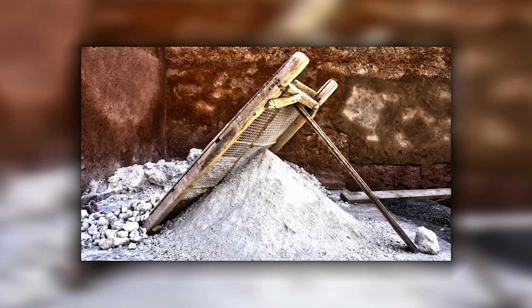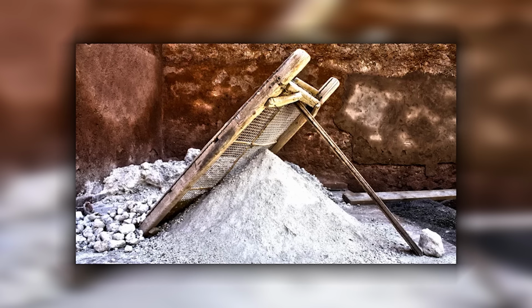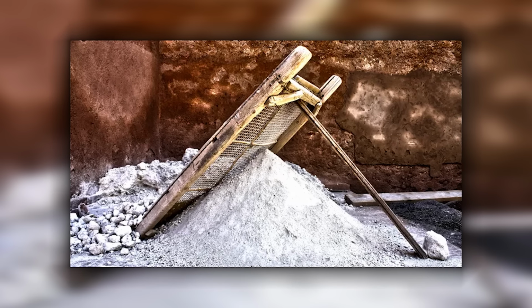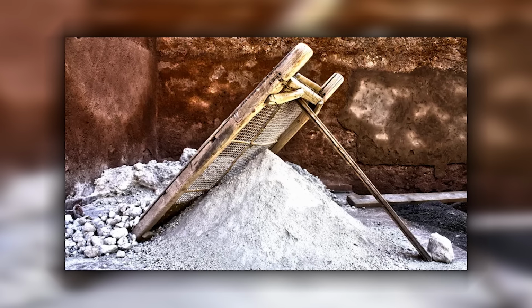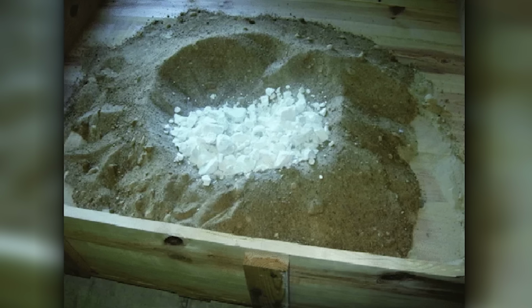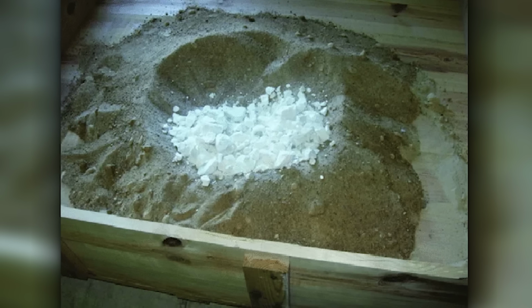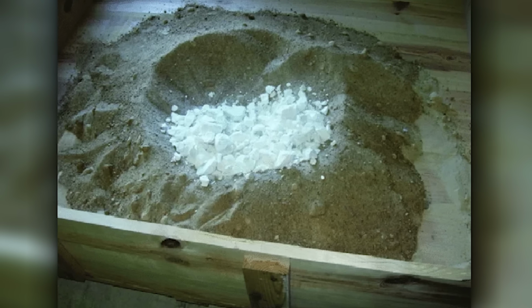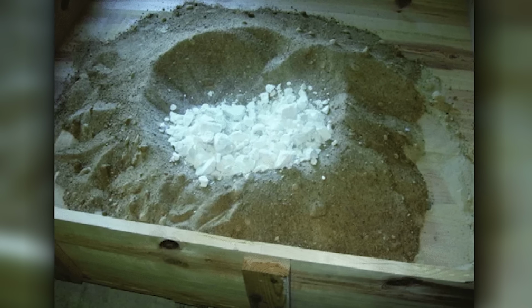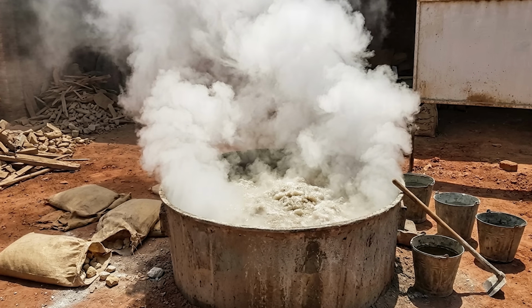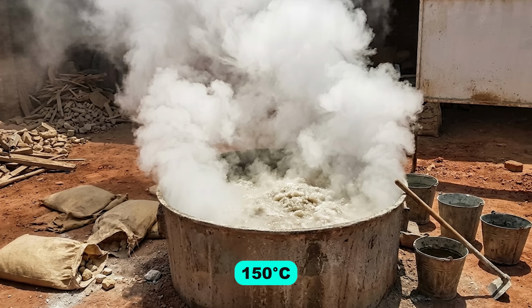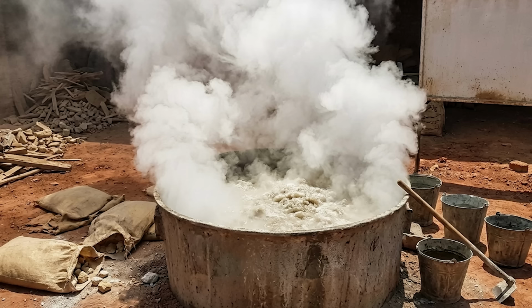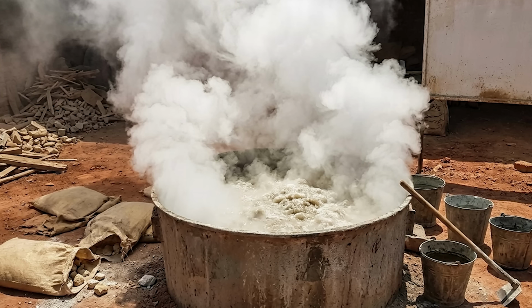They started with quicklime, calcium oxide, the hot caustic powder you get straight out of a lime kiln before water touches it. They mixed the dry quicklime directly into the pozzolana and the aggregate, then added water last, all at once. The reaction is violent. Quicklime hitting water reaches 150 degrees Celsius in seconds. The mix steamed for hours.